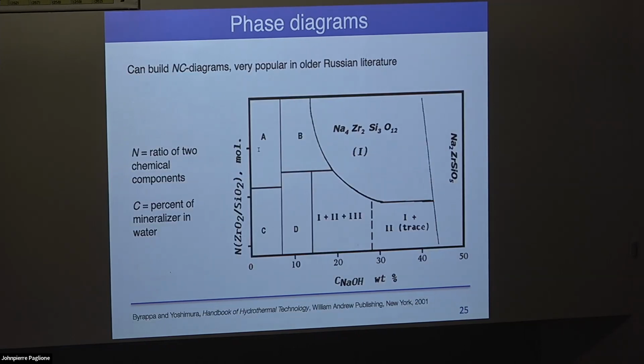Some other phase diagrams you'll see, one that you might see in older literature, not used too much now, is called an NC diagram. Basically it's the ratio of two of the chemical components of whatever solution you're trying to make, and the percent of mineralizer and water. The mineralizer in this situation, the system was sodium hydroxide, which is helping with the dissolution and the formation of the products. And the N is a ratio of zirconium oxide and silicon oxide. Basically what they do in these systems is they plot the different species that are being formed in this phase space. And that way you have a much more predictive understanding. If you wanted to exactly make this phase, you have to be in this concentration regime. So the NC diagram is essentially the concentration analog of the Pourbaix diagram without considering electrochemical potential at all.